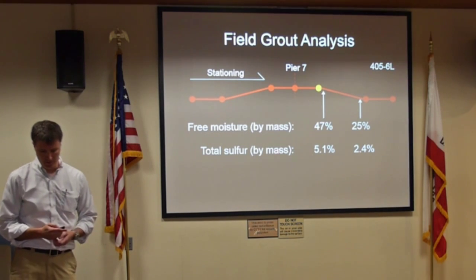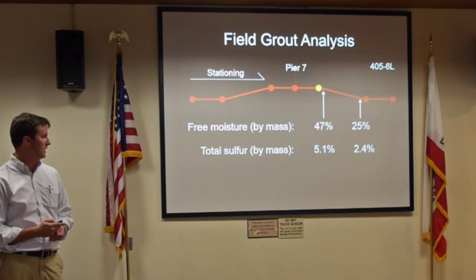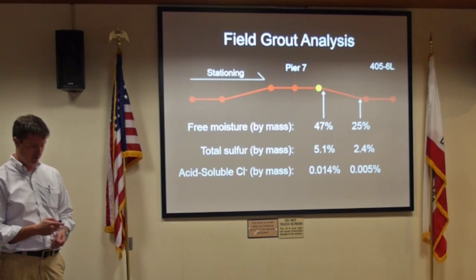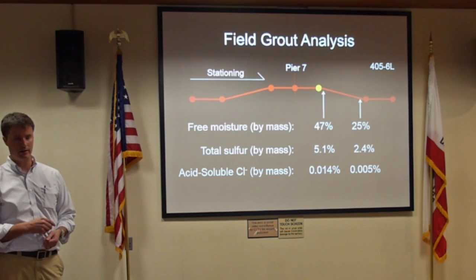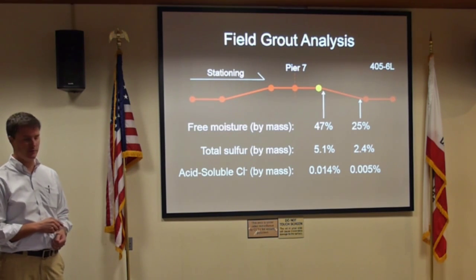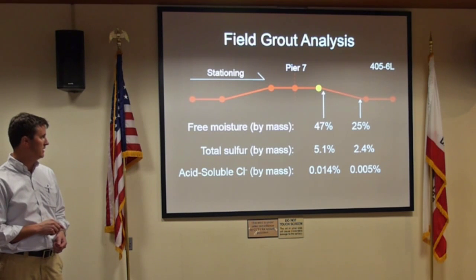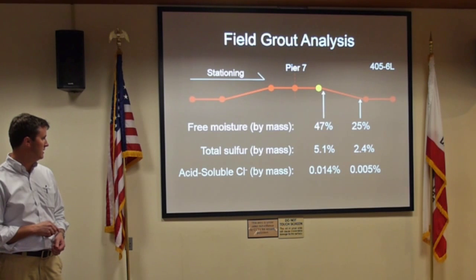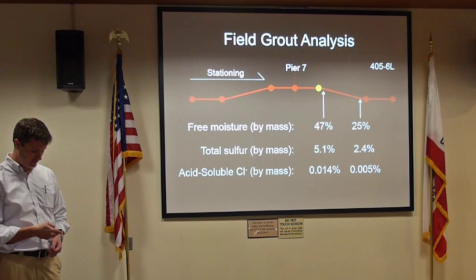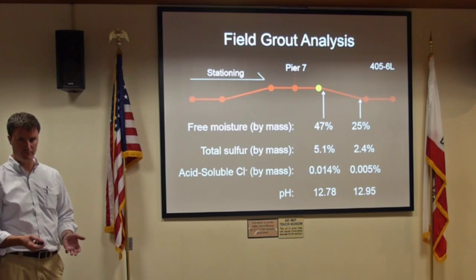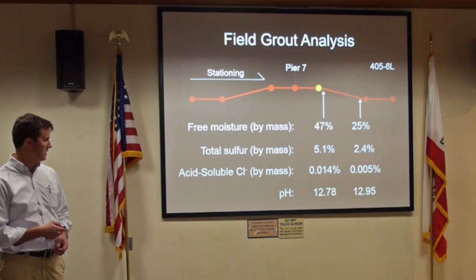And so we ended up really focusing on the grout here, and what we found is that along the profile of the tendon, the properties of the material of the grout actually change. Here at the low point, there's less moisture than at the high point. The concentration of sulfur is higher at the high point. Chlorides, like I said, generally bad for corrosion, also higher.